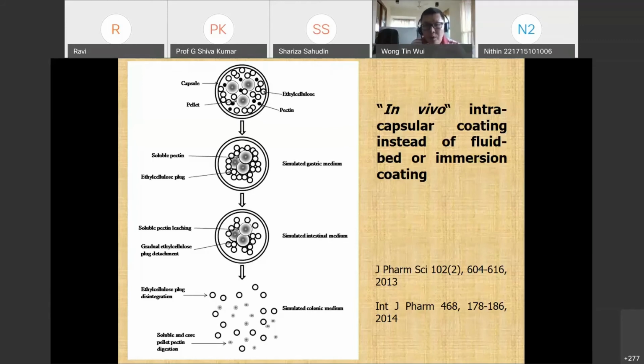And in the colon, what happens is that we have a lot of microbial enzymes, and these microbial enzymes can actually digest the pectin of the pellets, as well as pectins from the coating powder mixture. So digestion of the pectins results in disintegration of the pellets, and the total release of the drug will occur and takes place in the colonic region. So this study is rather interesting because it adopts a very simple technology, and hence you can actually achieve the same outcome.